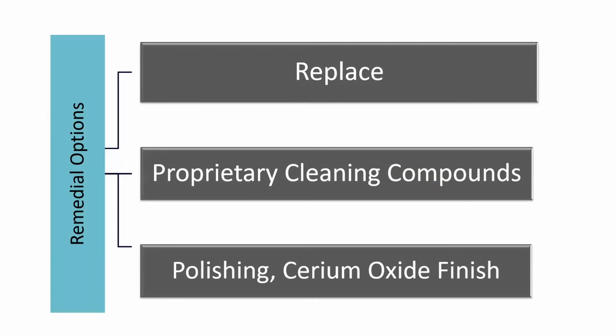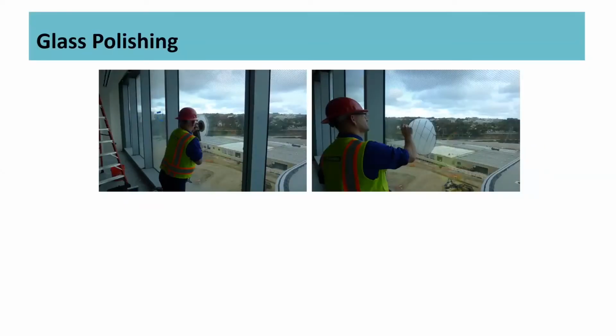So we've identified how we can get the blemishes, and then we've also taken a look at how to identify which are objectionable or not allowed blemishes. What do we do about that? Well, the no-brainer solution would be to replace the glass, but as we've discussed earlier, that can be a very costly proposition given the types of glass, the types of glazing, the access, etc. Secondly, as we've seen in one example so far, proprietary cleaning compounds have caused more damage than good in most cases that we've seen, particularly cleaning compounds that have silica or hydrofluoric acid in them. So that leaves polishing, a procedure where the final process involves a cerium oxide type of finish. So let's take a look and see how that process works.